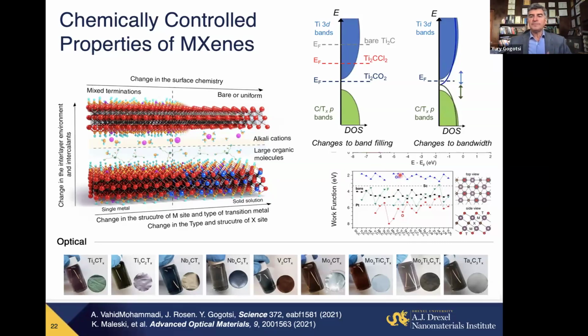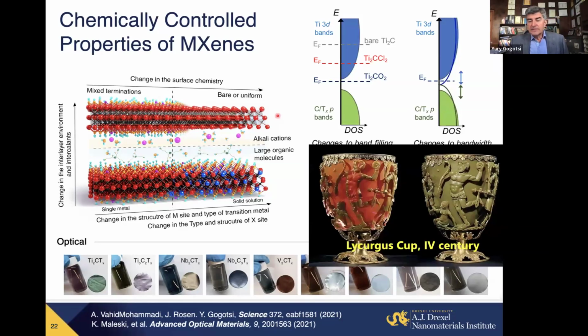We are applying less than 1 volt potential when we have protons and water between the layers of MXene. And this is possible because the density of states in these materials is not as high as in copper or gold or other conventional metals. So by changing surface termination, we can change it, like in a semiconductor. So basically, those are two-dimensional metals which, like semiconductors, can have modulation of properties during work, which opens really new opportunities. And let me give you one example of many where MXene can replace gold, silver, other expensive elements.